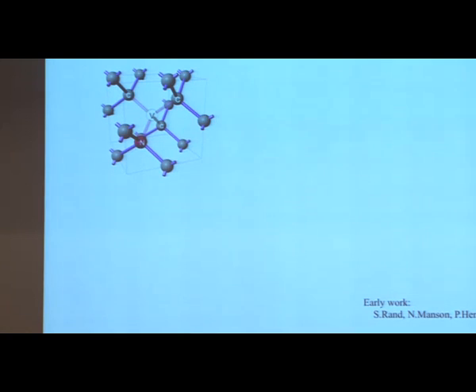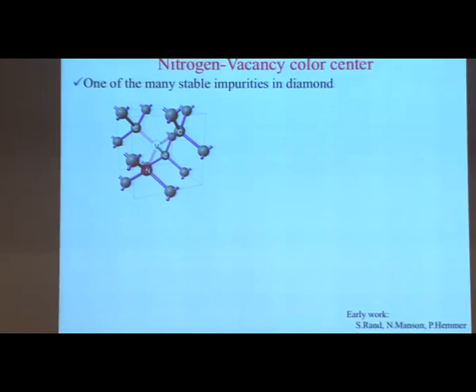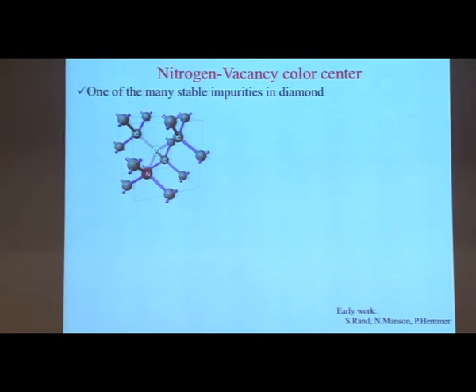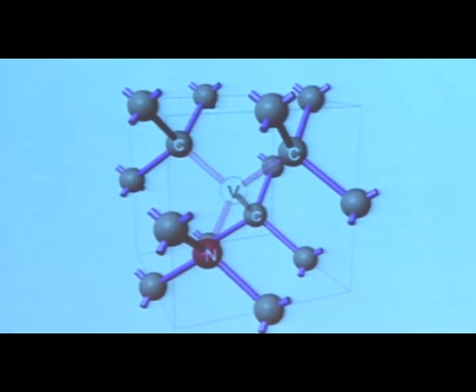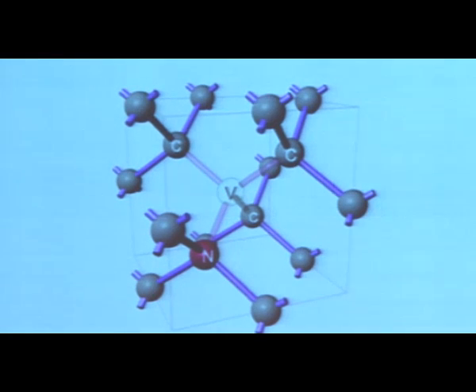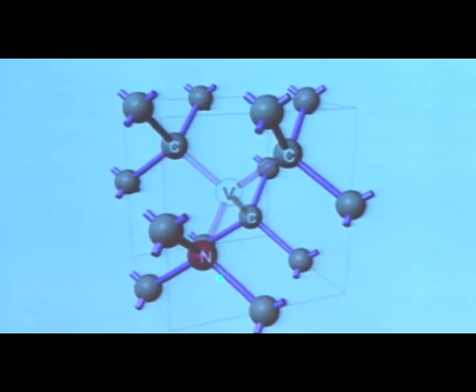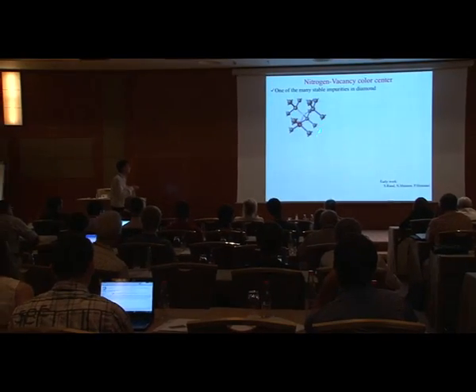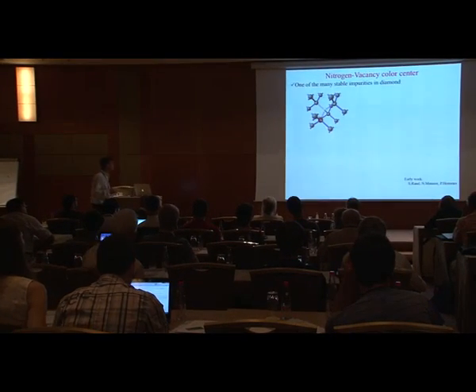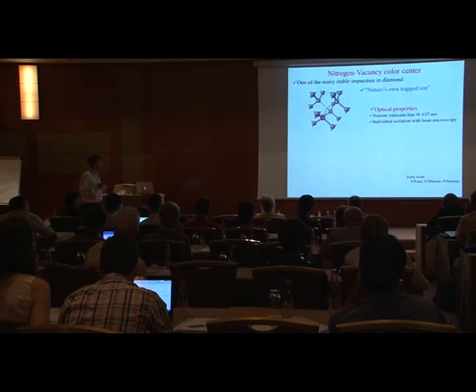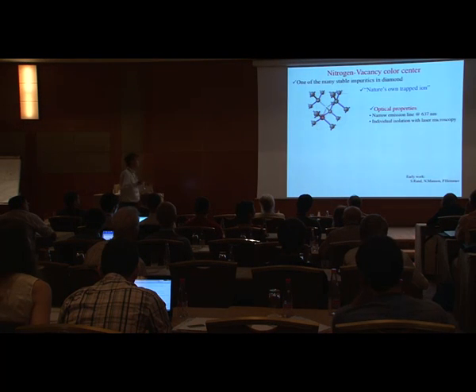So what we do in our work is that we make use of one impurity inside the diamond crystal, which behaves like a single artificial atom. This impurity is the so-called nitrogen vacancy impurity. It consists of a nitrogen atom which substitutes a carbon atom in the diamond lattice and a nearby vacancy. And basically, this becomes like a nature-made qubit. So it's just a single atom embedded in the diamond crystal.